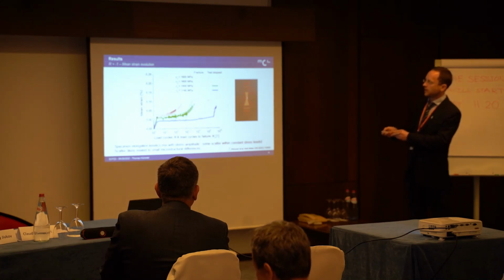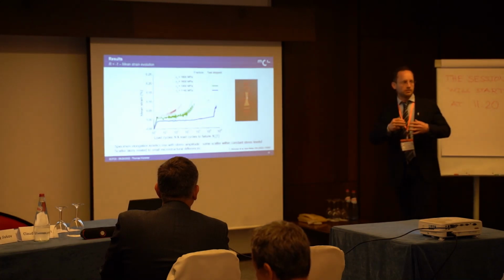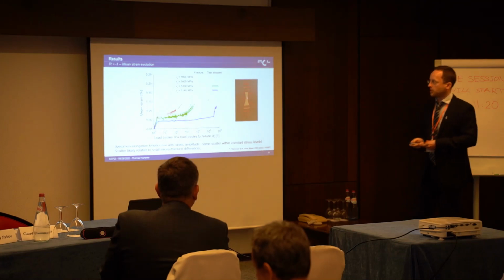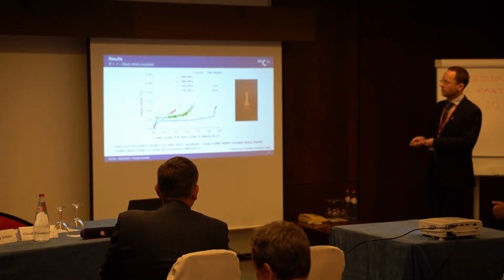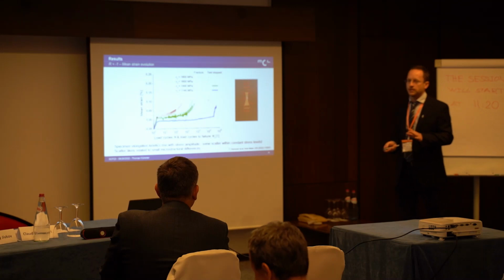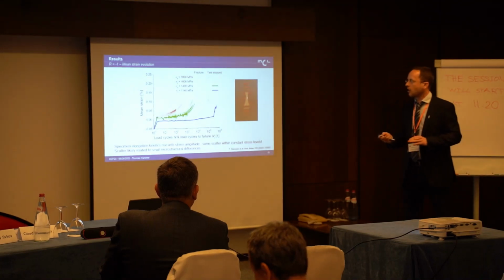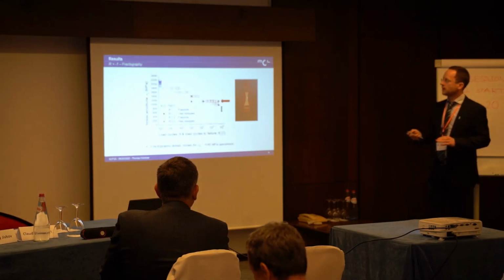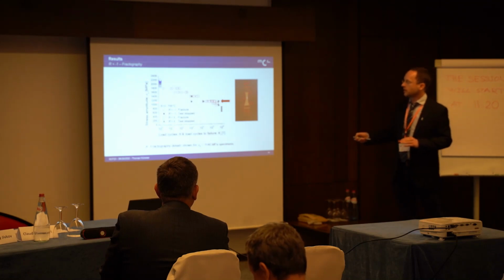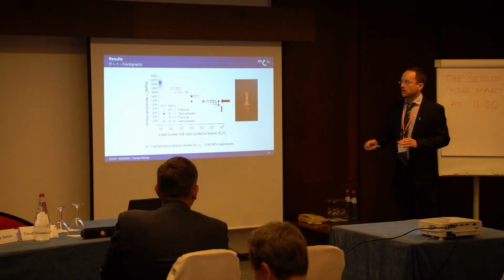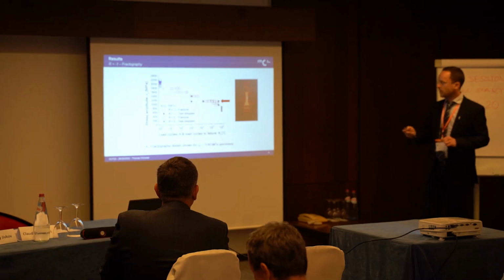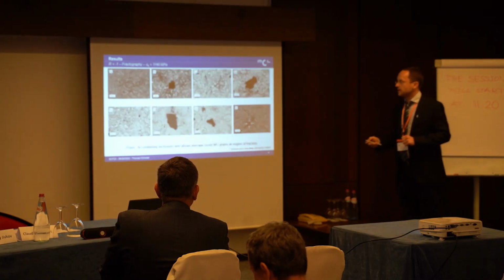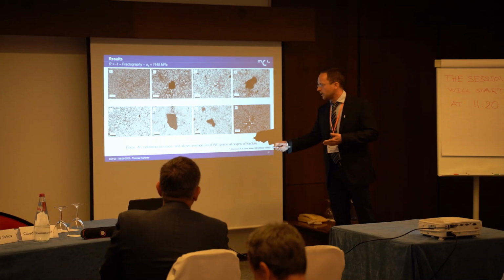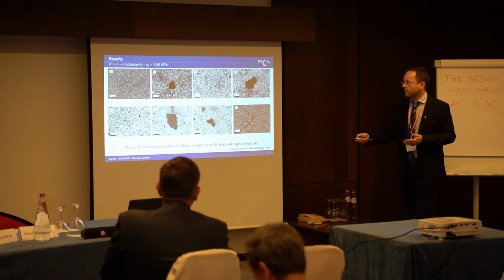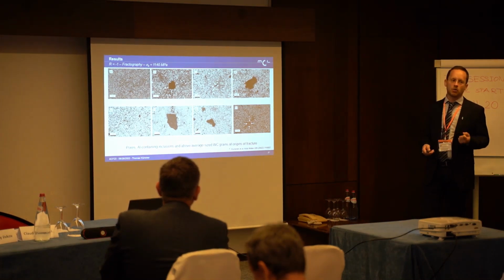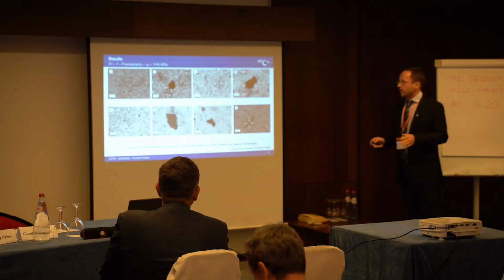But I want to draw your attention to this individual scatter within one stress amplitude. And this has to do, I think, with small microstructural differences. And this is also relevant for fractography, as I'll show you in a second. For this load case here, say close to the fatigue limit, 1,100 megapascal stress amplitude, what we see here are porous aluminum-containing inclusions, and again also these above average size tungsten carbide grains at the origin of fracture. So far, so good.